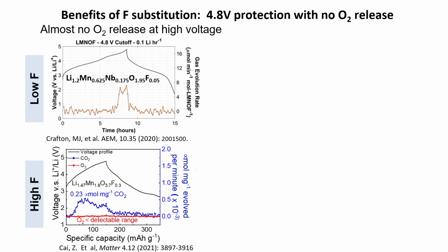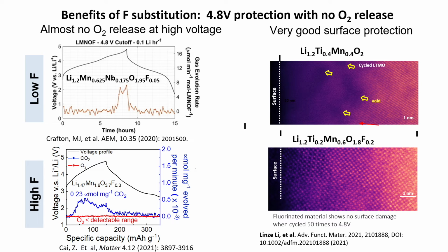The reason that gas coming off is important is that it tends to swell the cell, but also oxygen gas is particularly bad because it's essentially an oxidant and you have an organic solvent that you can combust with it. So there is an extremely small amount of oxygen coming off, and that's because fluorine passivates the surface.